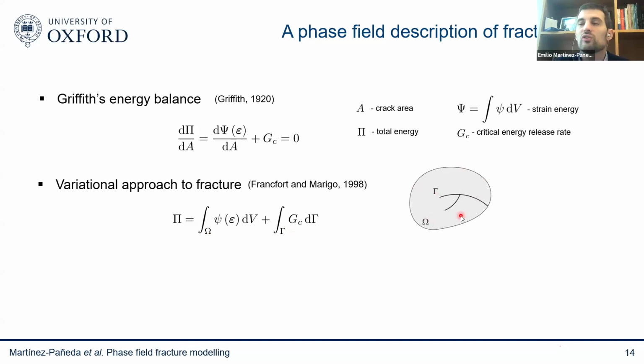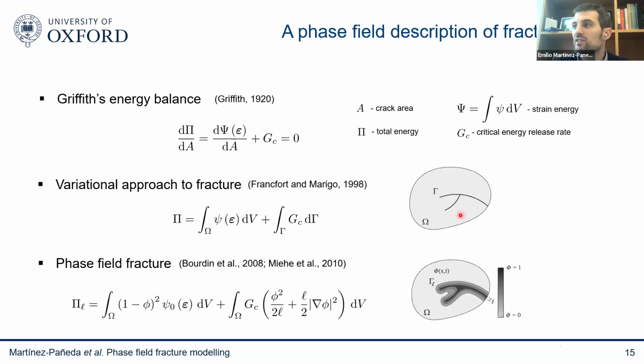So what you can do is to use the phase field paradigm. The phase field, this auxiliary variable, goes from 0 in intact material points to 1 in fully cracked material points, and then varies smoothly in between. So it's a little bit like a damage variable. It goes from 0 in points that are not damaged to 1 in fully damaged points. And like a damage variable, of course, it reduces the load carrying capacity. This is the strain energy density that, of course, depends on the strains. And then it's a little bit like a non-local continuum damage mechanics model, in that you have a gradient of the phase field, which naturally brings a length scale, and I'll discuss this length scale later on.